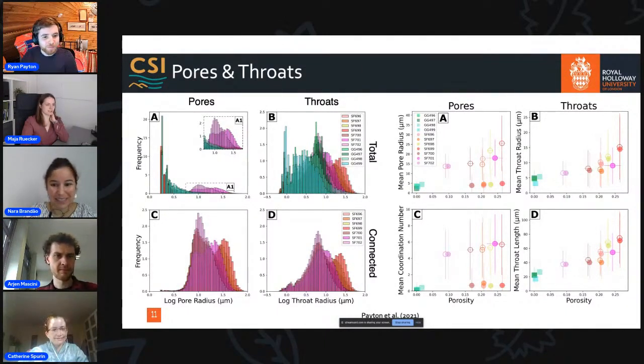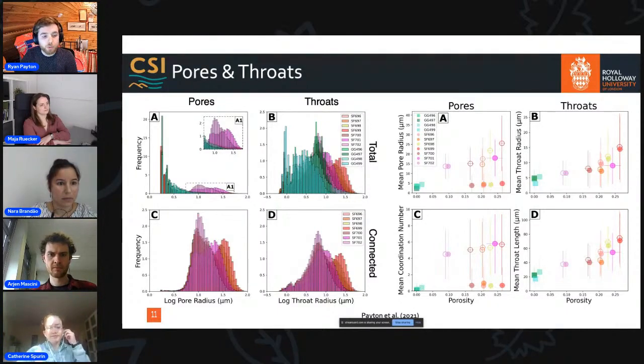Okay, so it seems like this question was answered. I have only one more question for the disconnected pores. Is it possible that these are still connected through micropores which you cannot see? And in this context, have you considered looking into some analysis like Arne proposed before to address this? Yeah, this is really important to consider. It's important to say that everything that I've presented is based on macro porosity. Because of the resolution of the images, we wanted to make sure that we were fully characterizing the samples, and microporosity is always a big part of that, because obviously, as we've seen, microporosity can control the overall porosity quite significantly. So we did some optical microscopy to have a look at some of the questionable areas which showed up in the grayscale images from the CT to try and see what was going on there.